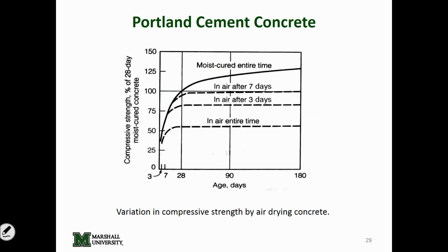The importance of properly curing your concrete. Do all the mix design in the world and get it perfect, but if we don't cure the concrete correctly, this is an indication of what kind of compressive strength you're going to get. Cast the concrete, don't do anything for it, dry it in the air the entire time. When you thought you were going to maybe get a 3,000 PSI concrete, you're going to get 50% of that. Your y-axis here is percent of the compressive strength at 28 days. So if you wanted to get the maximum value out of your concrete, you moist cure it, keep it cured when it's going through its hardening process, and you will get more than 100% of your design strength. So the longer you leave it out, the lower your compressive strengths are going to be.